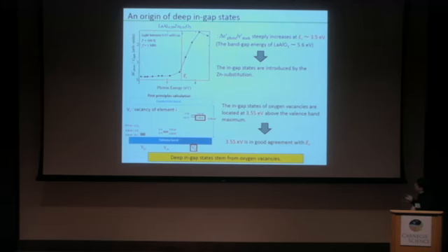This is excitation energy dependence of unconventional photodielectric effect at 1 MHz. The horizontal axis indicates excitation energy, and vertical axis indicates the relative change of dielectric permittivity. You can find the dielectric permittivity increases steeply at 3.5 electron volt. This energy is lower than the bandgap energy of lanthanum aluminate. This result indicates that the in-gap states are introduced by the heterovalent zinc substitution.